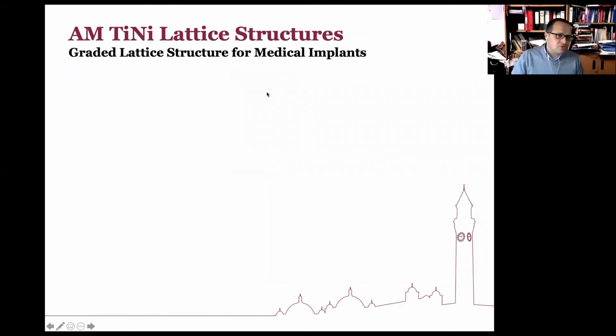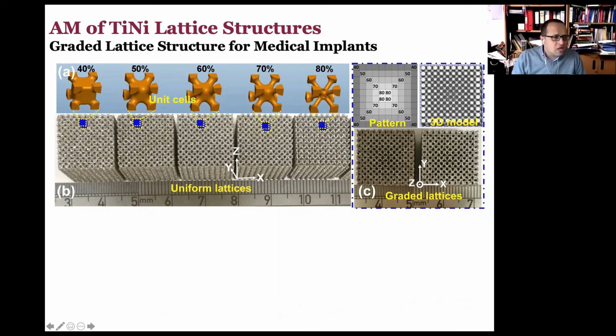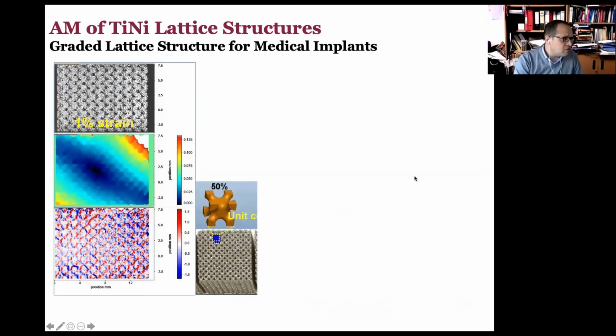Lattice structures and the uniform arrangement. And this is the example of the graded lattice, where the porosity in the middle is different from the porosity at the edge. When we looked into their mechanical loading, we found that the material that has the uniform lattice usually has that 45-degree densification behavior.